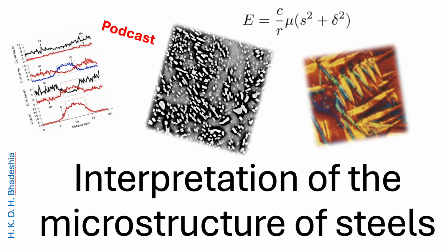And you see this kind of element partitioning constantly in commercial alloys. Think about the problem of a banded microstructure in steels with manganese, or Mn. Which is most of them. Most of them. During cooling, Mn segregates. It creates Mn-enriched and Mn-depleted bands. Ferrite prefers low alloy content, so it forms in the Mn-depleted regions, and the carbon gets pushed into the Mn-enriched bands, which then transform into these continuous bands of pearlite. And you get that distinct, structurally variable pattern.